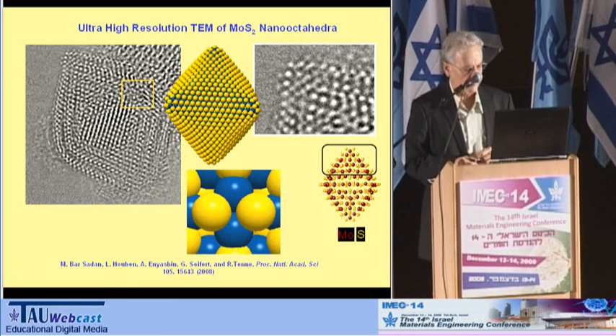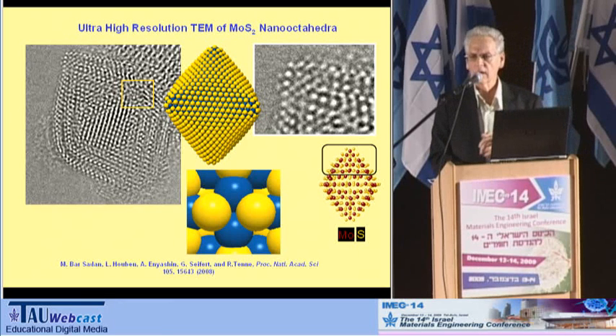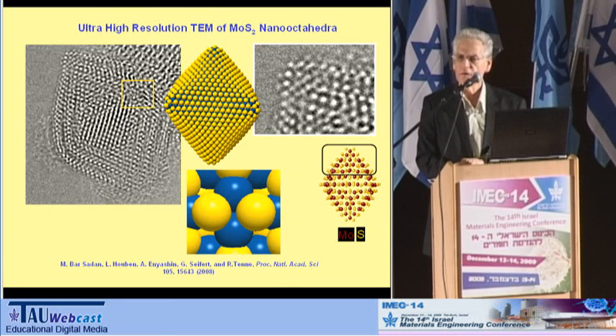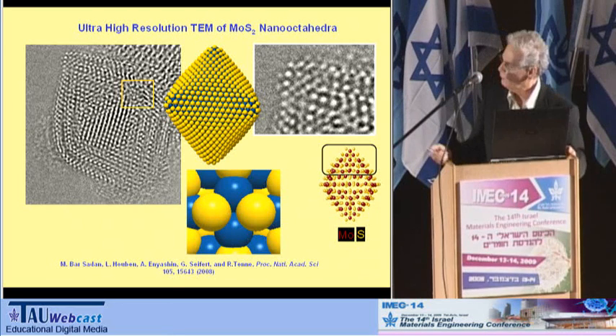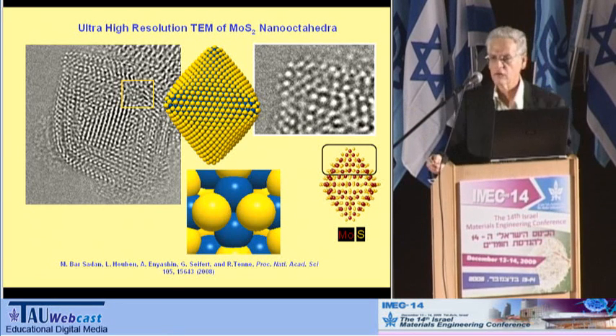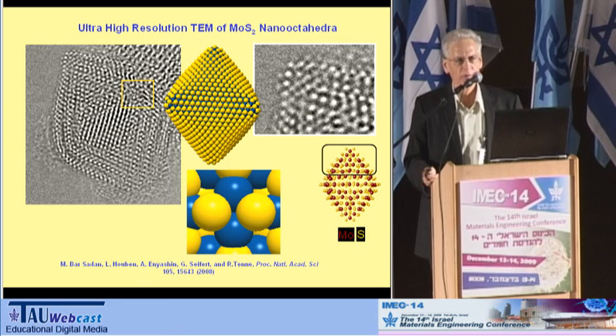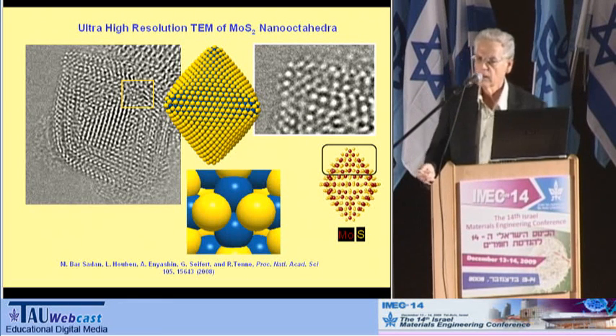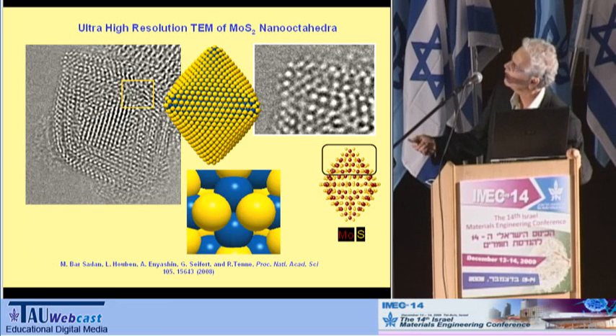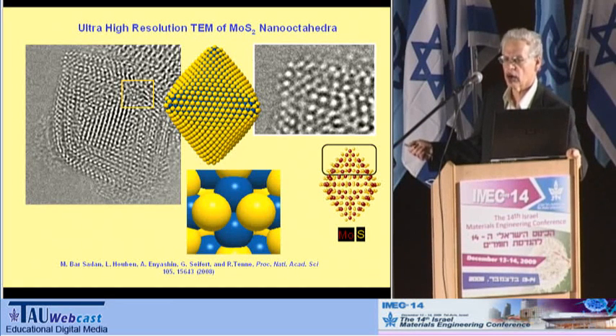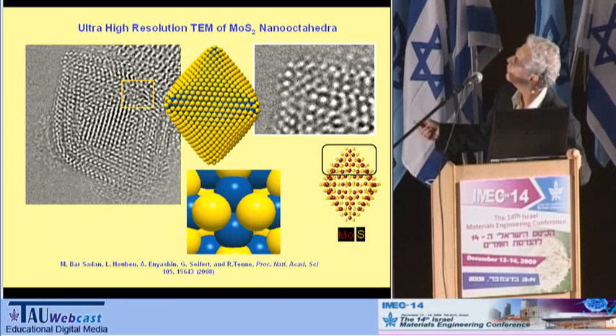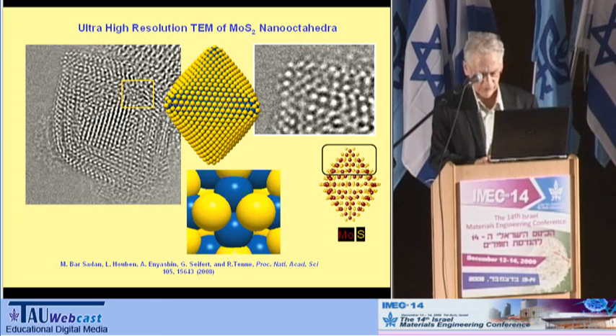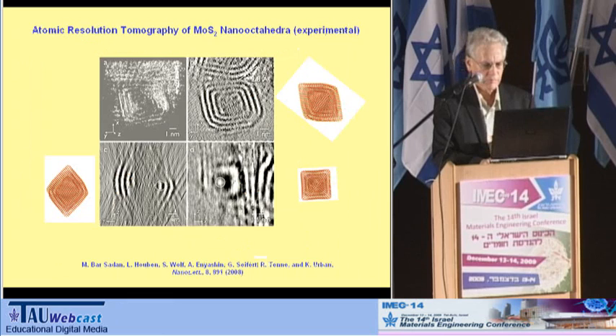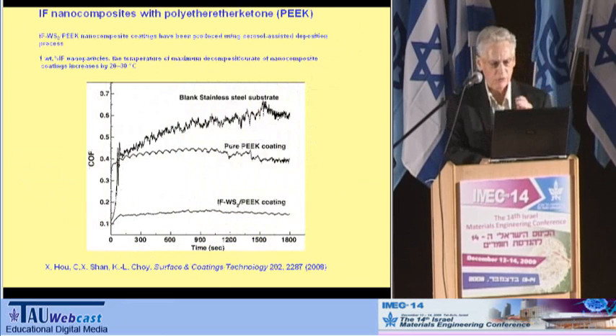This is a bigger structure than the C60. Usually it's about 10 times larger in terms of size and in terms of number of atoms. If you look at this structure, it consists of about 600 atoms of molybdenum and about 1,200 atoms of sulfur, and it's made of octahedra. Again, using CS-corrected microscopy and a quantum mechanical calculation by Gotthardt Seifert, you can superimpose the observed structure on the calculated structure, and you see a very good agreement between the two. So this is the superposition, and I think that with that I would be able to conclude my talk.